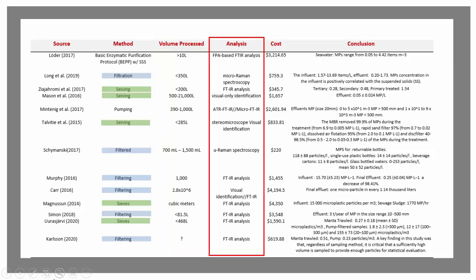Because we are spectroscopists, we chose to stick with the analytical methods, typically involving micro FTIR and micro Raman, but there was one that looked at stereoscopic visual identification. These visual methods of identification are grossly inaccurate. They're unable to distinguish one plastic polymer from another. We've even seen some where they use a hot pin to touch the plastic particle and see if it melts. If it does, well, then it's confirmed plastics. But really that has all the scientific integrity of a coin toss and should be discarded.